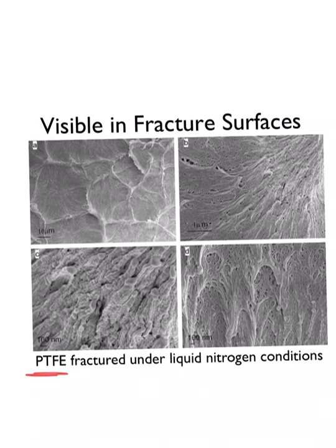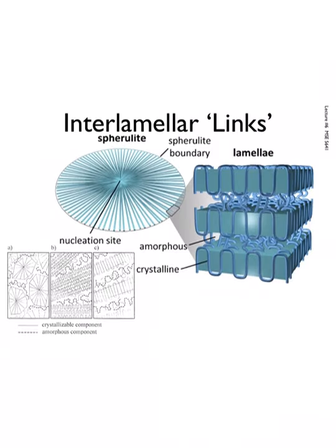But usually, as I said before, fractography of polymers gives you no information whatsoever. And this is one of the things that frustrated people back when they were trying to look at what plastics are, what their structure is. It didn't do what inorganics do. You can't look at transgranular fracture, because first off, there are no grains. You can't even look at transspherulitic fracture because it doesn't cooperate like grains do.